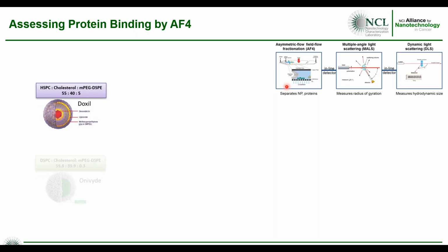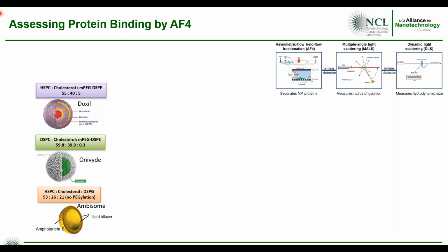We can also look at protein binding. Like I mentioned, you can run AF4 with and without plasma proteins, and AF4 can separate free plasma proteins from your sample. So in this case, we're doing AF4 with MALS and DLS inline. And for this, we're going to look at 3 commercially available liposomes: Doxil, Onivyde, and AmBisome. And I've also given you the lipid composition for each of these 3. The main thing here is to look at the lipid PEG. So in Doxil, we have about 5%. In Onivyde, 0.3, and AmBisome has no PEG at all. We want to take each of these samples now and run it as is through our AF4 and then after plasma incubation.